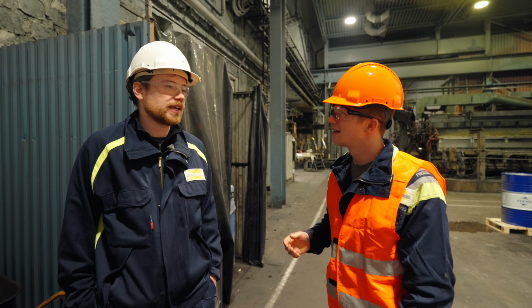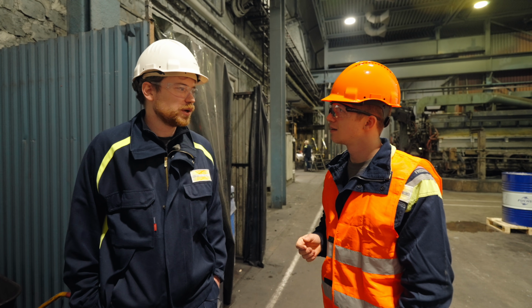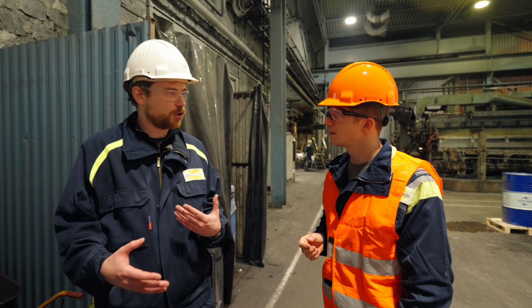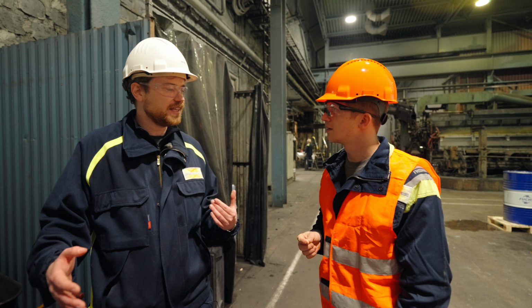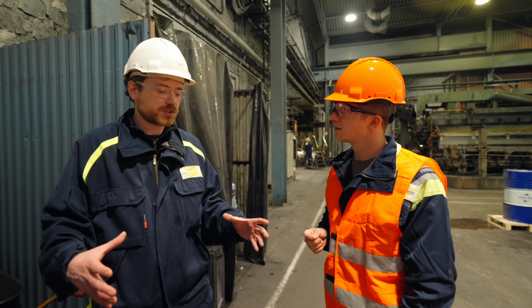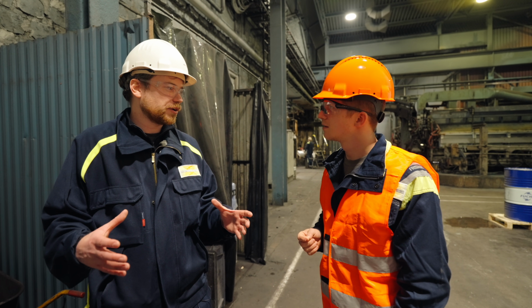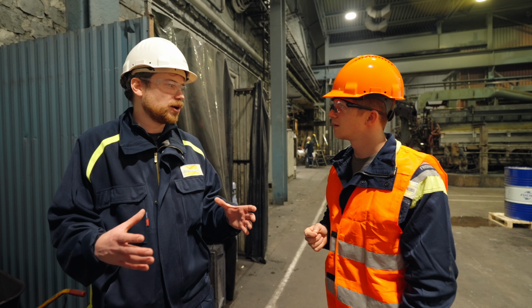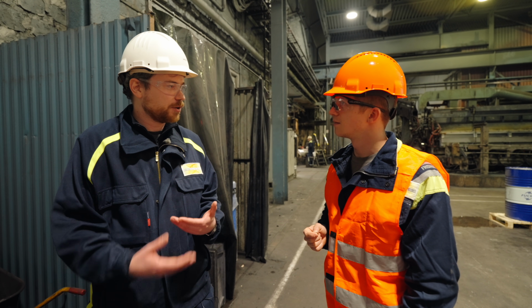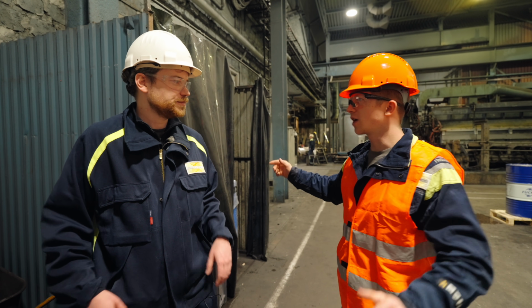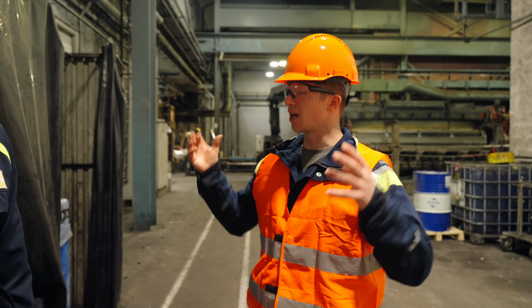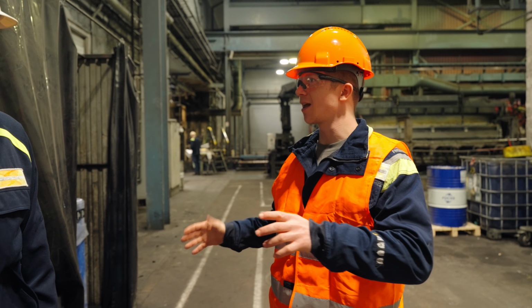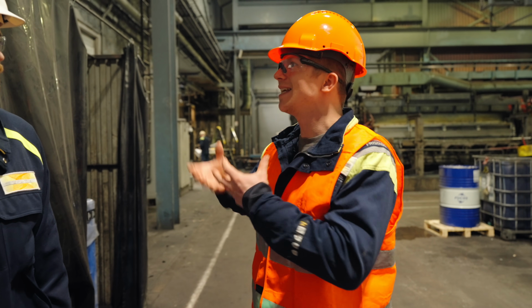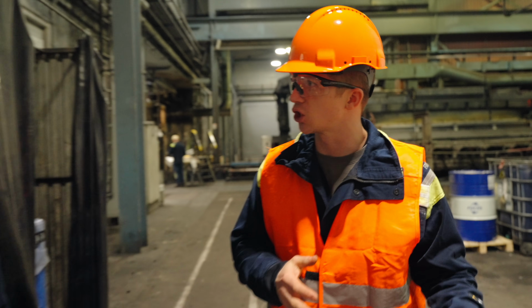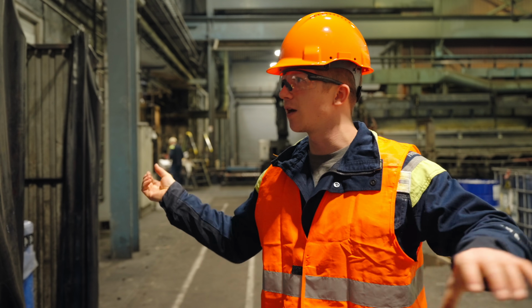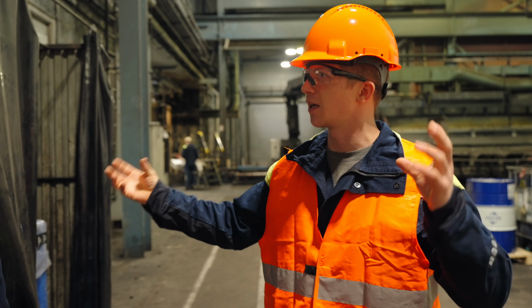Exactly. And with conventional steel making, you can achieve that by a lot of reduction. So when you forge it out, you can actually start to break down the carbides into smaller, rounder carbides and get a very even distribution throughout the bar. But you start with a cross-section that is similar maybe to what our capsules are, which means that you need a certain amount of reduction ratio to actually hot work the material through with a conventional steel making. Whereas here, you can have your capsule like this. It comes out of the hot isostatic press. You can slice it off and you could make something from it at that stage without needing to do that reduction as you would when you make a traditional ingot that then needs to be rolled down a significant amount to stretch out those stringers into something consistent through the whole bar.